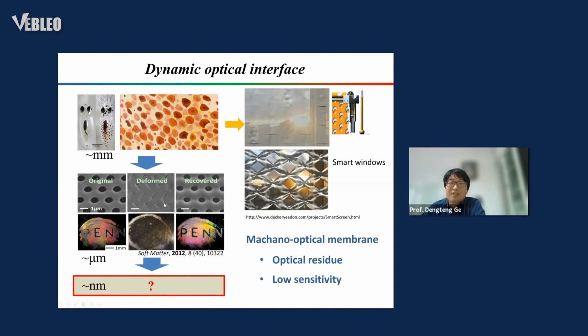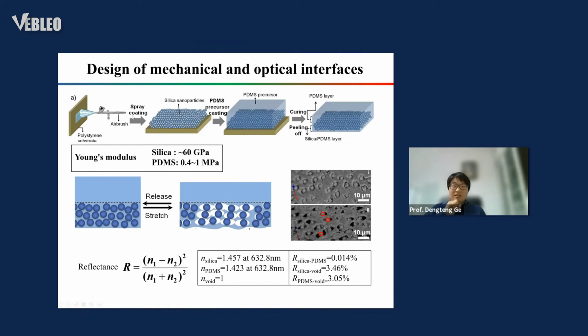To solve the first problem, we think that if we want to avoid seeing the optical residue, we can reduce the size. If the size is lower than 100 nanometers, the scattering is out of our eye's visible range, so we couldn't see it. So here, our strategy is to use silica and PDMS to make a composite system.